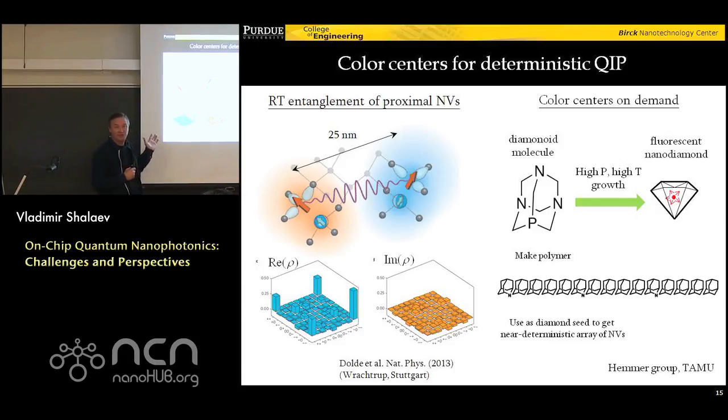In the case of the nitrogen vacancy, you do have a long-living coherence time for the spin degree of freedom at room temperature, but a very broad photoluminescence line. In the case of silicon or germanium, you have a very narrow spectral line, which could potentially be used to demonstrate a room temperature source of indistinguishable single photons, and our group and other groups are working on this. But in terms of the coherence time of the spin degree of freedom at room temperature, it's very short. So we're still looking.